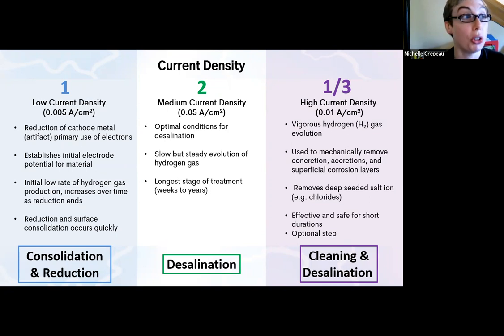Your low current density is generally what you start with. It's usually your first step. It's how you determine what your initial electrode potential is for the material. This is basically how you figure out what the lowest current is that you need to start the reaction. Like, how many electrons do you need to invest in the system before you get any type of reaction at all? And this is heralded by a release of hydrogen gas, but it's very slow and inconsistent. That hydrogen gas, as I mentioned earlier, is a really good indicator of when your reaction is happening, to make sure that reduction is happening at your cathode, since hydrogen evolution occurs there.